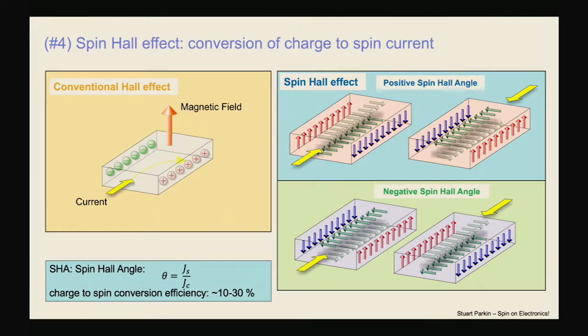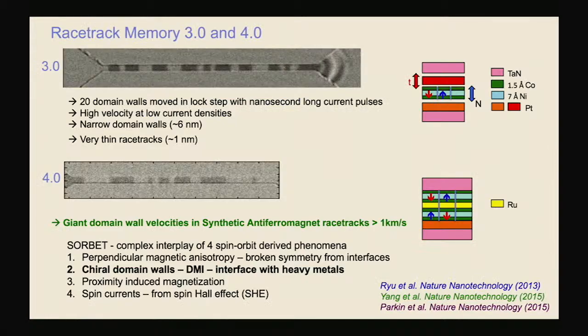And the spin Hall effect is also a chiral effect. And it's the combination of these chiral effects that really makes it possible to use currents to switch them to spin currents. These spin currents diffuse into these chiral domain walls. And because of that chirality, all the domain walls along a racetrack will move in the same direction. And as we've demonstrated, up to speeds of more than 1 kilometer per second at useful current densities. This is why racetrack is interesting.